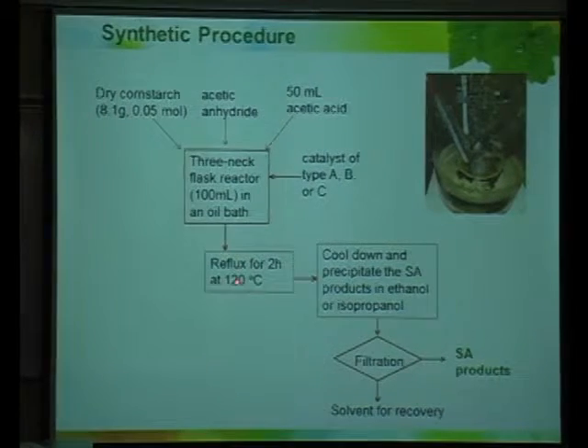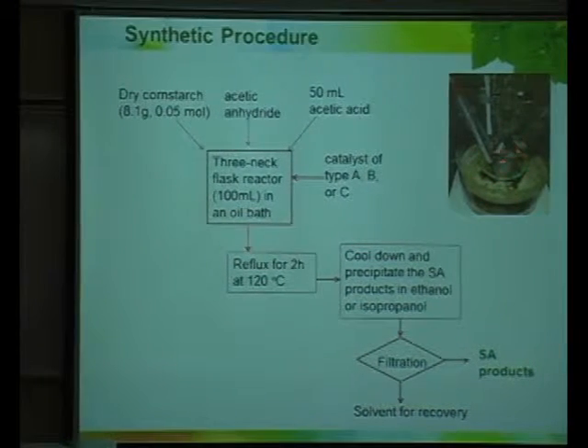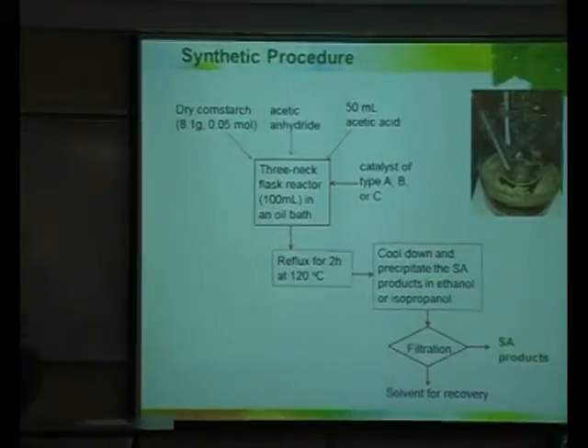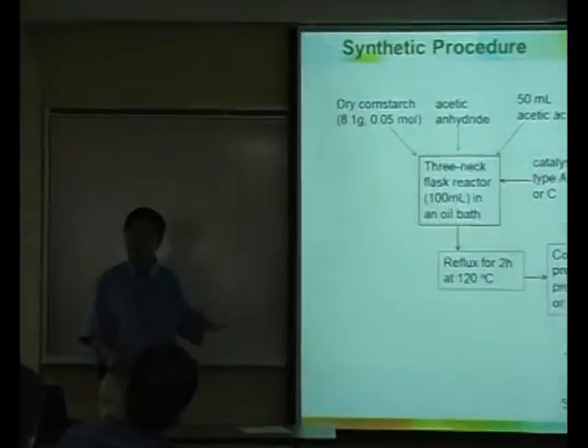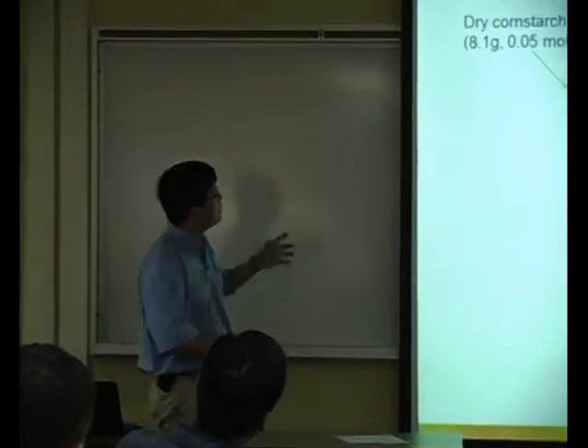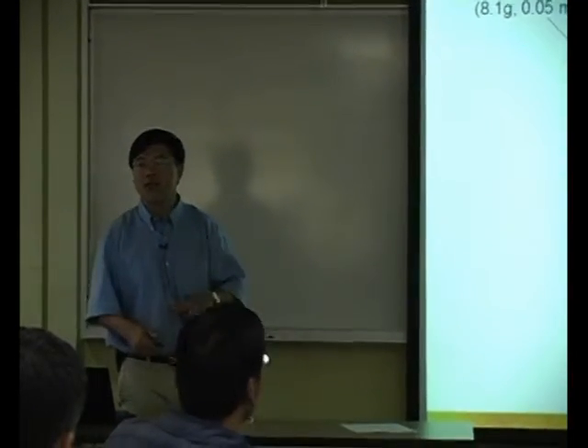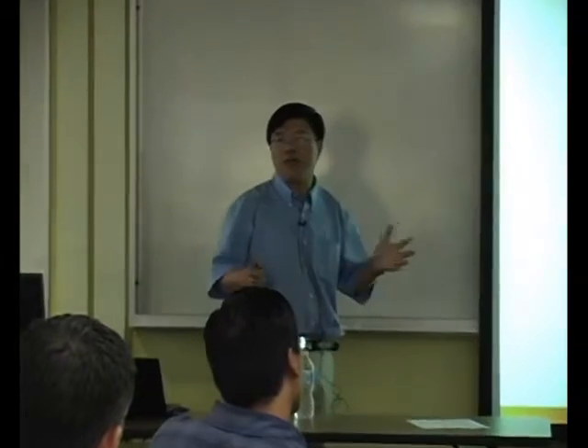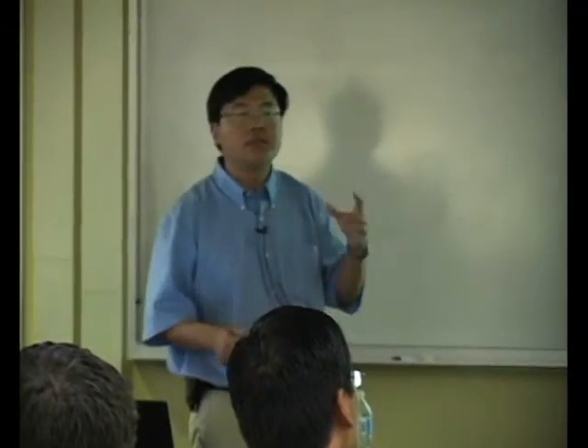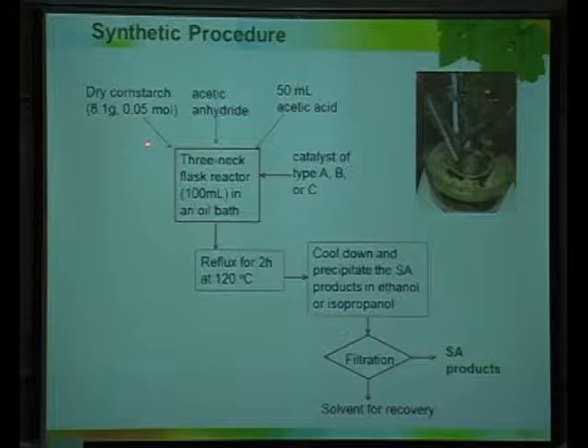With a reaction temperature of 120 for 2 hours, we can get the starch converted almost completely. Normally starch, if you dissolve it in water, is a slurry. But after the reaction is done, it becomes a clear, transparent solution. We cannot see the color. That's the product, starch acetate. So we can do the separation and get the product, and the solvent acetic acid can be recovered. So that's the beauty: we do not produce byproducts or a waste stream.